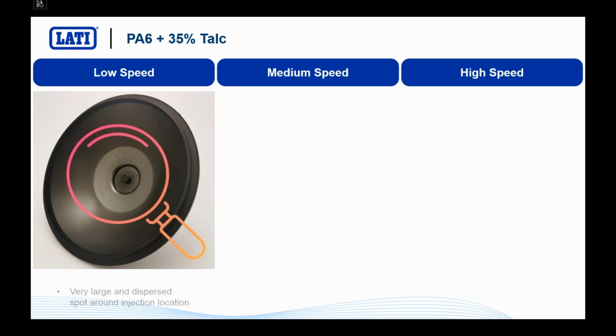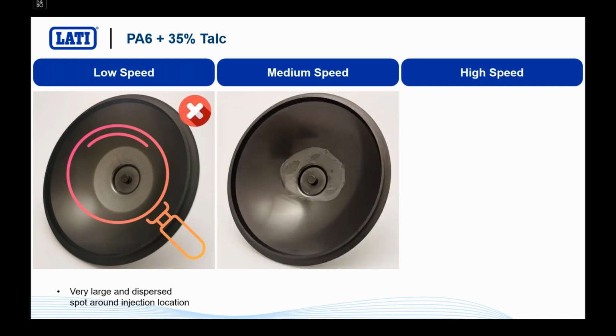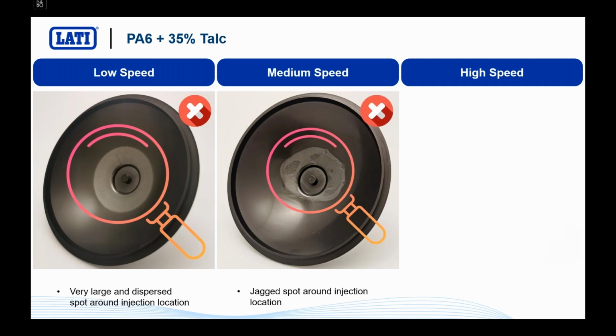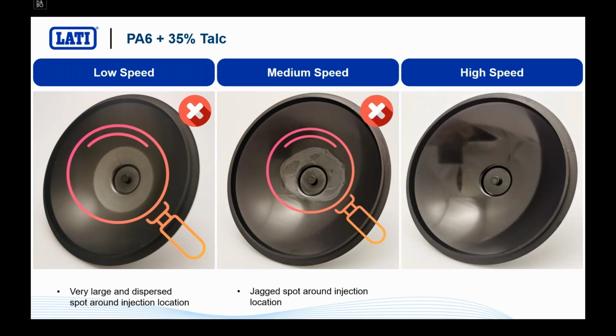The same stuff. You see the same trend, so you have a very bad looking nasty spot below, which is looking even worse at medium speed, but it will completely disappear by increasing the speed. So with the same material, with the same geometry, with the same tool setup, you can actually achieve a perfectly looking surface finish just working on the injection speed, moving from a low speed to a high speed.